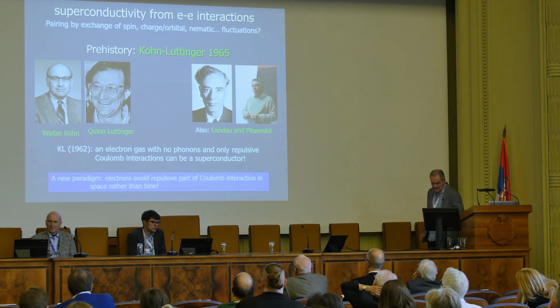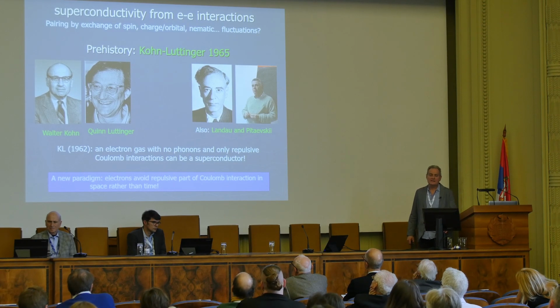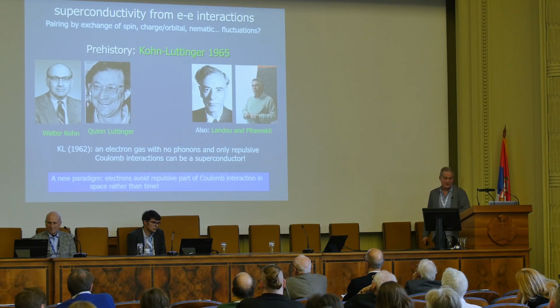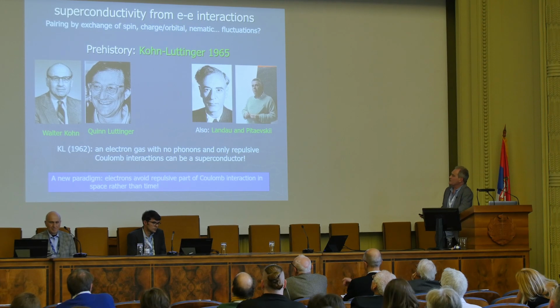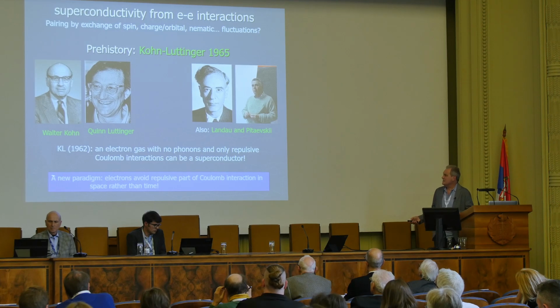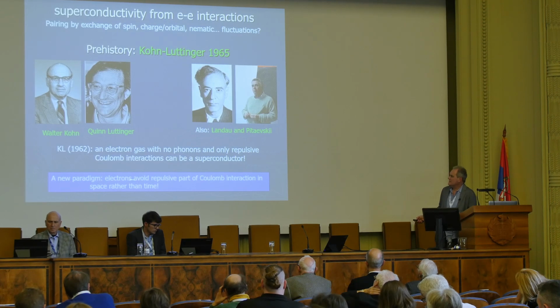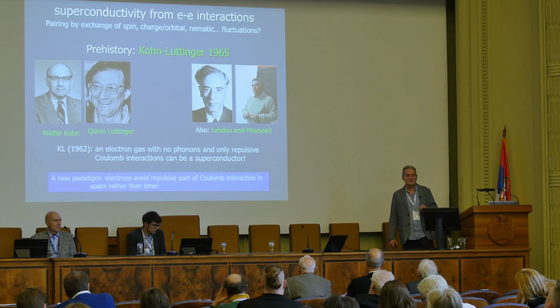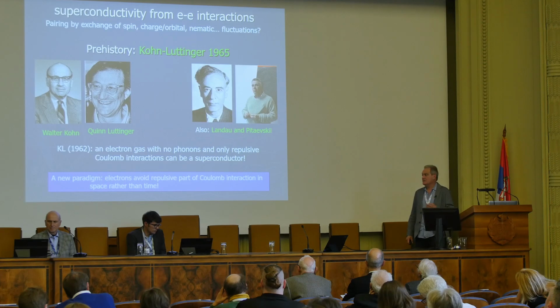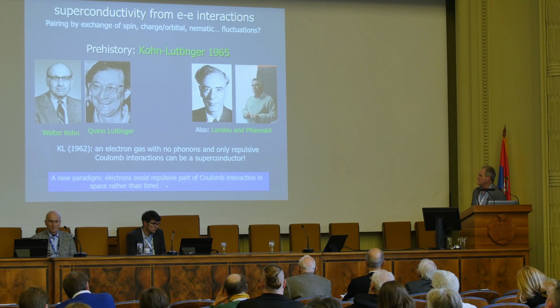Okay, let's go back a little bit to the theory of how you can get superconductivity from repulsion. A very strange idea. But in fact, it's quite old. It goes back to these gentlemen, Walter Kohn and Quinn Luttinger, in 1965, and very similar ideas from Landau and Pitaevsky in the Soviet Union at the same time. The statement, which is very clear, is that you take an electron gas model, no phonon interaction whatsoever, you have only repulsive Coulomb interactions, and that system has a ground state which is superconducting. And the idea is a new paradigm for superconductivity, which is that the electrons avoid the repulsive part of this Coulomb interaction, not in time, as I showed you before, but rather in space, because they exist in a particular kind of wave function that helps.